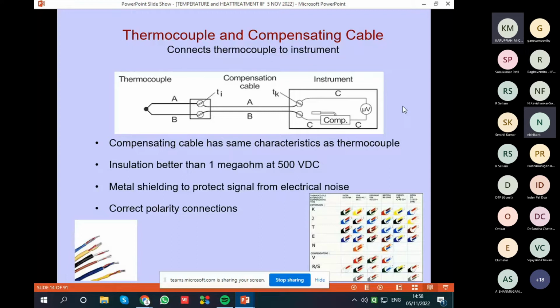That is why these compensating cables are very important, and try to use metal sheathed cables so that they are protected from electrical noise. Especially if you are taking temperature on the shop floor in the molten bath, it is better you have a metal shielded cable, because you are very near to the induction furnace or electric arc furnace, and those signals should not be picked up by this thermocouple. The voltage is very small, of the order of some millivolts.